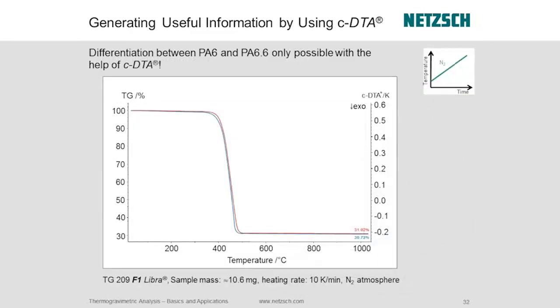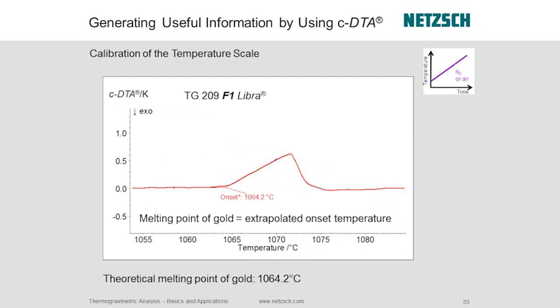Okay, and here's a good example of that. I showed you two slides ago the different polymers and the degradation and how they were nicely separated. Well, guess what? Here's nylon 6 and nylon 6-6, and their degradation falls pretty much right on top of each other. It's hard to tell one from the other, okay? But with that CDTA, the calculated DTA capability, we can tell very nicely, based on this melting temperature, that one is nylon 6, polyamide 6, and one is nylon 6-6, polyamide 6-6, okay? So that calculated DTA is really excellent as a technique, as a feature to add some horsepower to your basic TGA work.